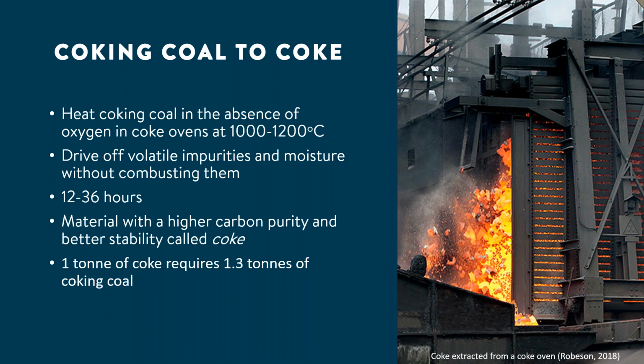The ovens can be top loaded or side loaded, and 30 to 70 of these slender ovens can be arranged side by side to form what we call a coke battery. One or more batteries can be used in parallel, depending on the scale of the plant, producing up to several million tons a year. Each oven is sealed, and the coal is then heated to 1000 degrees centigrade, or roughly 1800 degrees Fahrenheit, in the absence of oxygen. The coal releases volatiles and moisture without combusting them, and these volatiles are then captured and reused elsewhere. After 12 to 36 hours of heating, the coal turns plastic, releases its volatiles and moisture, and then cools into a mass with a very high carbon content.